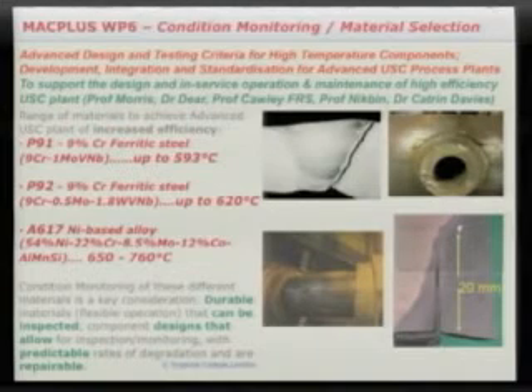These things are pressurized to very high pressures, a couple of hundred bar, and very high temperatures, typically 580 degrees C. But if you're talking about raising the temperature of the steam to up to 700 degrees C, then you need to use high temperature materials, and really you're in the game of nickel-based alloys. The guys at E.ON have done some calculations on this and worked out that to build one of these power stations, you're going to use the world's supply of nickel in 1 year. So the reality is it may not be nickel that is used. Probably more likely is the chromium ferritic steels and pushing those to higher temperatures with coatings and other technologies.